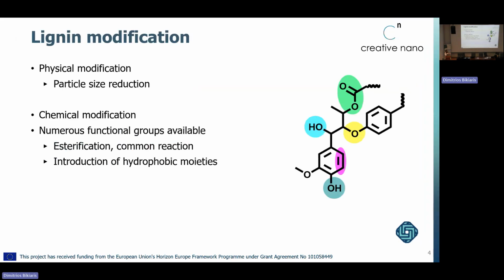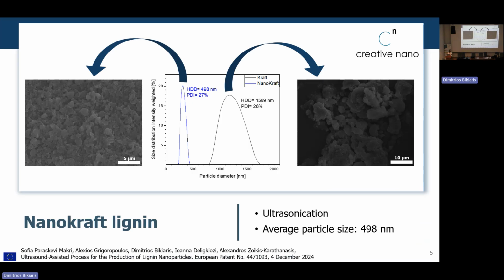To solve some of this problem, we can modify lignin, so we can have a physical modification which leads to a particle size reduction, and also chemical modification on the numerous functional groups we can have in lignin, for example, the hydroxyl groups or the ester here. And one very common reaction is the esterification of the hydroxyl group, which decreases the hydrophilicity, and therefore we can achieve a better compatibility. In the context of the REDONDO project, Creative Nano has performed a physical modification by producing nanokraft lignin, which has particles of about 500 nanometers, and this was achieved by a patented method using ultrasonication.